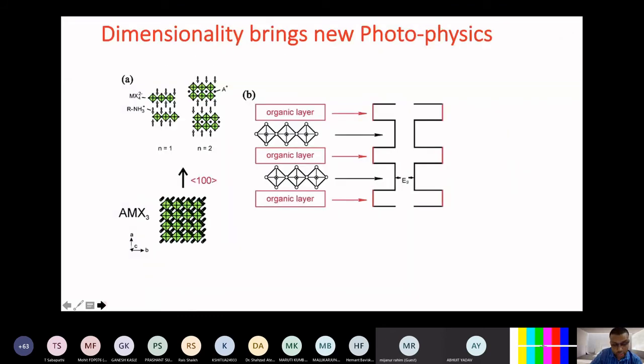So that was 3D perovskite, but if you use some organic cation much larger than FA, then the perovskite structure collapses and you can make a layered structure. This is what is shown here, n equal to 1, n equal to 2. If you have a much larger molecular cation, you end up with a single sheet of inorganic lattice, separated by a large band gap organic lattice.